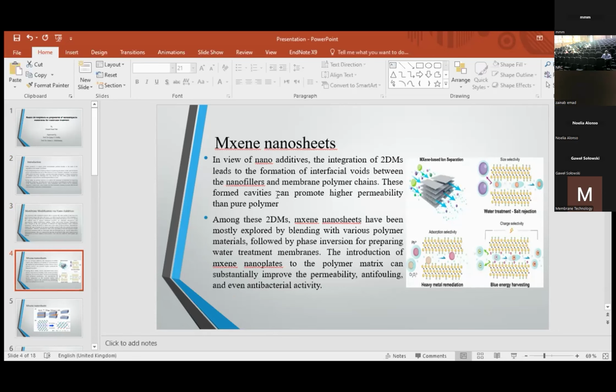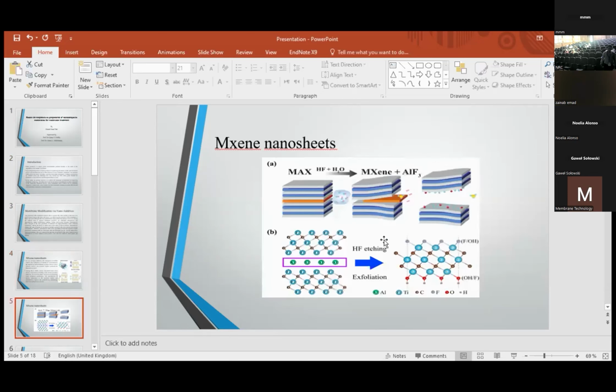Among these two-dimensional nanomaterials, MXene nanosheets have been mostly explored by blending with various polymer materials, followed by phase inversion for preparing water treatment membrane. The introduction of MXene nanosheets to the polymer matrix can substantially improve the permeability, anti-fouling, and even antibacterial activity.